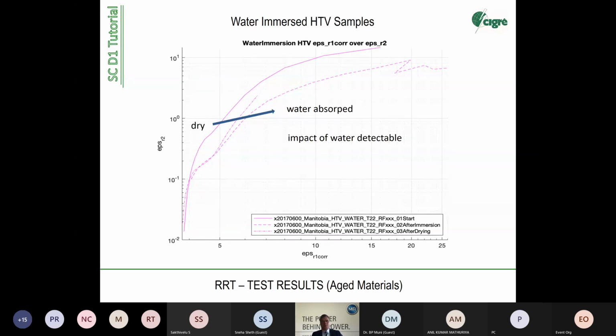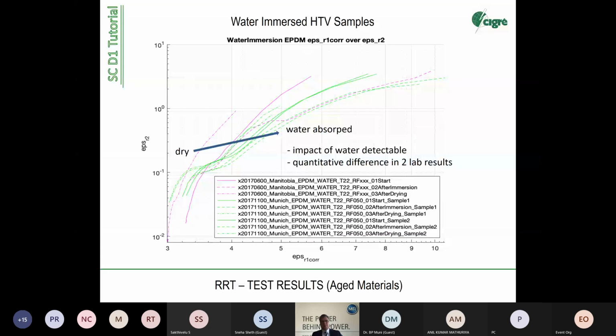Not a surprise here because besides the polymer matrix, the filler is the same. We see impact of water also here. It's affecting both. It's affecting the loss situation because you dissolve alkaline sodium ions. They are still in the minerals. You never get them out completely. And of course, you have water at the interfaces. Water itself has an epsilon R of 81. So any kind of water in this interface will increase both epsilon 1 and epsilon 2.